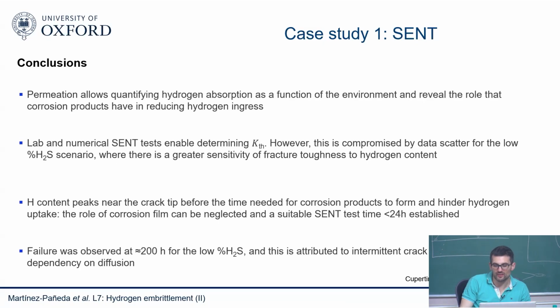The only thing that we can think of what could happen is that, so we see that we get a steady state hydrogen in 20 hours, so what happens in 200 hours? The only thing we can think of is that maybe we get crack growth, intermittent crack growth, they see that in the experiment, and when your crack grows, the hydrogen is following your crack, so the competition between diffusion and crack growth, the hydrogen can get farther thanks to crack growth as opposed to an unstable cracking process.